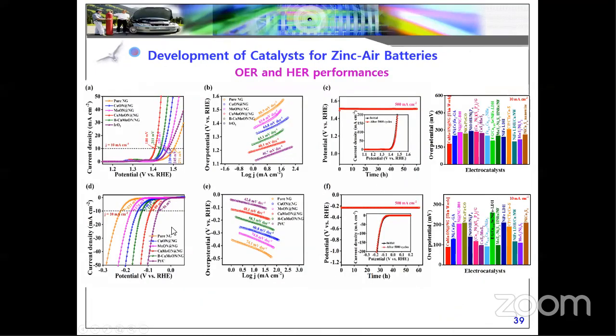And for the OER as well as HER properties, as per the previous discussion, you can see our catalyst for OER versus iridium. Previously ruthenium was used, but iridium is more active than ruthenium in the aqueous KOH media. That's why we chose iridium for this work. The iridium based catalyst has a higher potential compared to our material. That's why our catalyst is better than the iridium based and other catalysts. The kinetics is very high, close to the iridium oxides, and the stability was confirmed by the chronopotentiometric test. And our catalyst's potential is lower compared to recently reported materials in the OER part. In the case of the HER, you can see the platinum carbon potential and our catalyst is almost near the platinum carbon, and other catalysts may be higher than our catalyst.